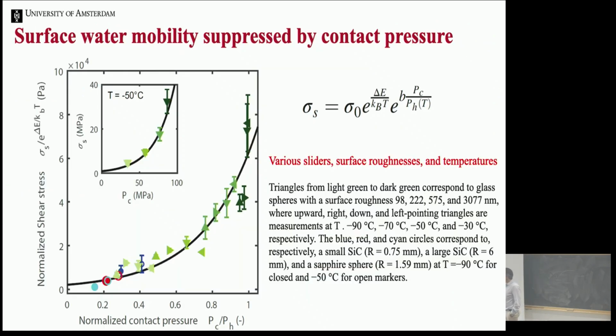And this is, to make a very long story short, the result of a lot of measurements at different temperatures and at different surface roughnesses, and also for 3 or 4 different types of material. Yeah, and so what I told you before the long break was that I thought that the friction force was proportional to some Arrhenius factor. Yeah, and the Arrhenius factor has to do with the mobility of molecules at the surface.